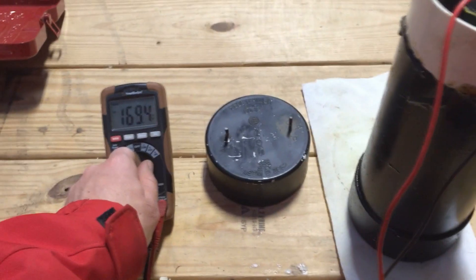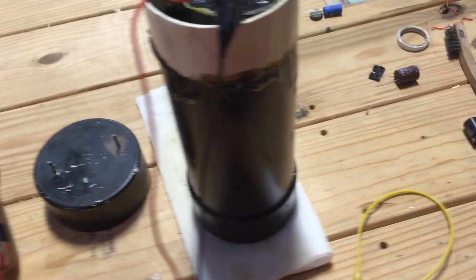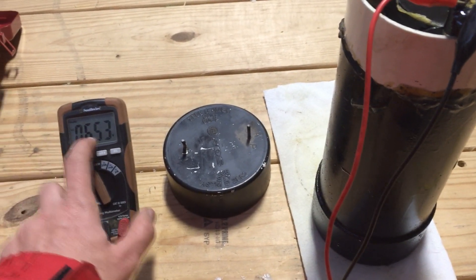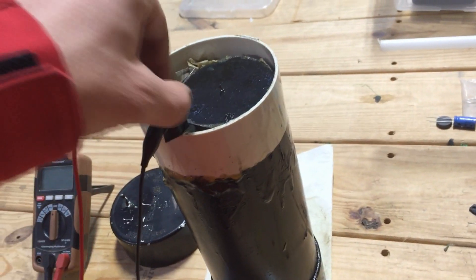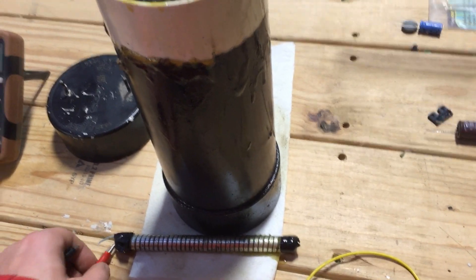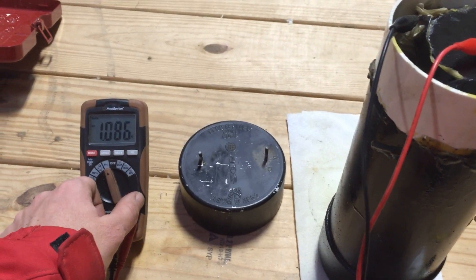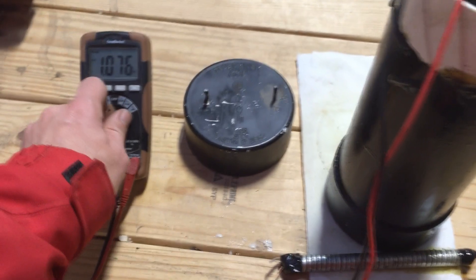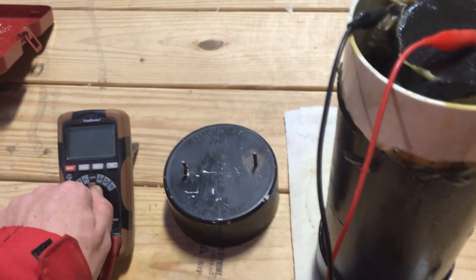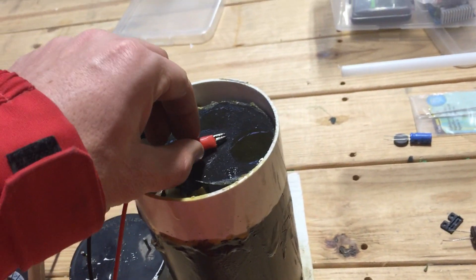The small one is putting out a little less than a volt, but it's climbing back up — I bet it's putting out around a volt. On the micro amp setting it's putting out about two micro amps, and this will climb back up to about a volt on this little cell. On the big cell we have about a volt — this is what they generally hold. On the micro amp setting we're at 20, which will probably go down and hold around 10 micro amps. It was adequate for driving ultra low current draw motors and jewel ringer LED type applications.